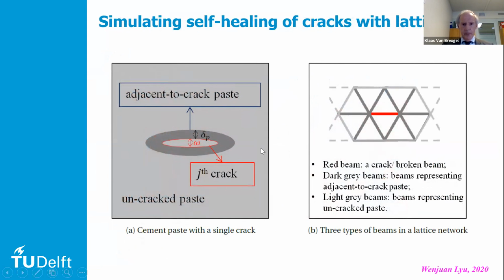You see a close-up of what happened around the crack. Here you have the crack. You have here around the crack some strengthening due to additional hydration. So suppose that you have a crack on the left picture, the right cartoon. The crack is indicated with the red lattice beam. Suppose that you are cracked, then the beams around will strengthen due to additional hydration. That's the idea.